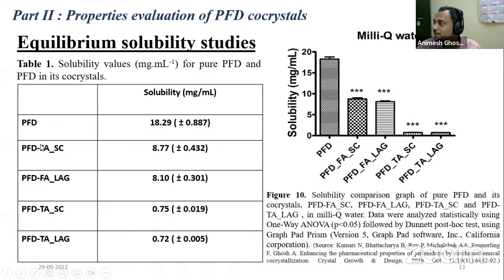SC means solution crystallization, that is, evaporative crystallization. LAG means liquid assisted grinding, that is, the mechanochemically synthesized one. For FA and TA, both from solution crystallization and liquid assisted grinding, we are getting almost the same solubility value. That means mostly a 60% reduced value. And in case of TA, it is very, very low, approximately 0.75 to 0.72.